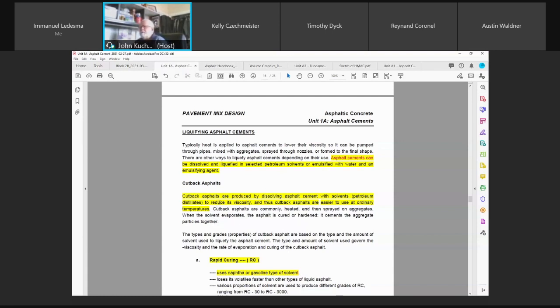And one of the ingredients that we use for cutting asphalt is, you see it sometimes used, well, maybe not so anymore because they're really stringent on that, but in the past, a lot of the trucks delivering hot asphalt would coat their trucks with diesel fuel, the back of them, so the asphalt will slide out. Well, if you're using diesel fuel, excuse me, to change the viscosity of your asphalt cement, if you're coating your box, that's going to change your mix. That's a no-no. So again, if you ever saw that on the job site, you would tell the contractor, you cannot use diesel fuel to coat your truck box so the asphalt slides out easier, because if you got that diesel fuel into your asphalt, it will start dissolving it.